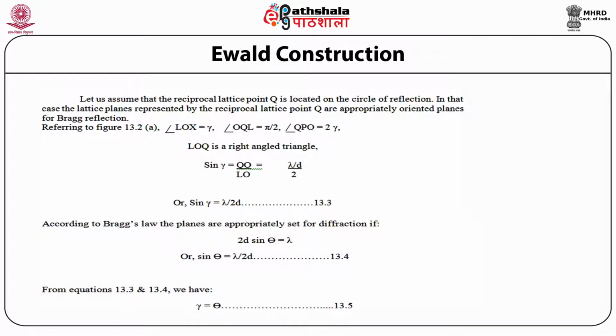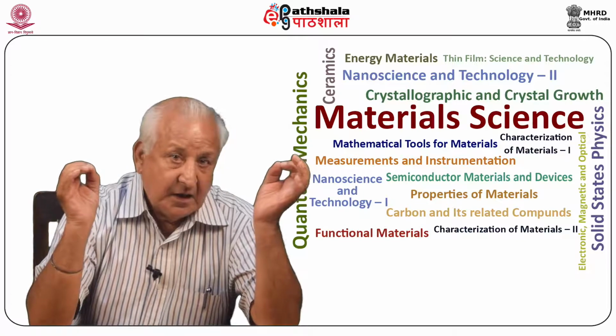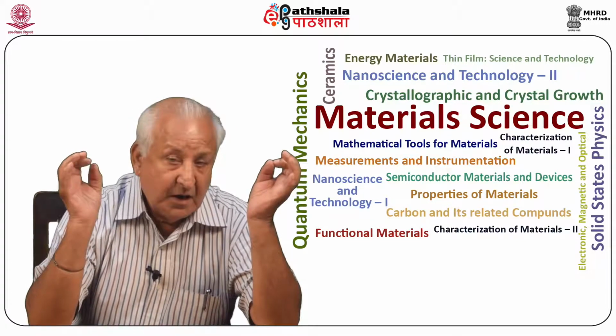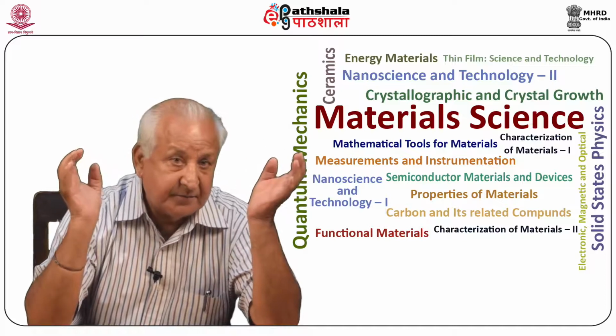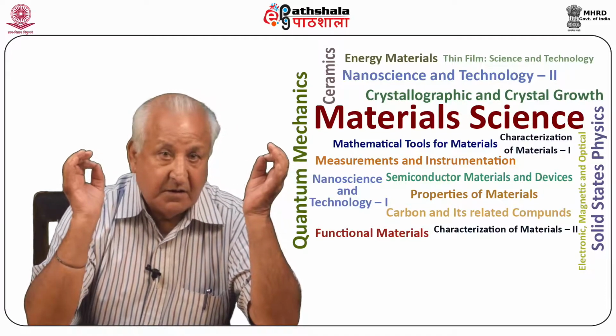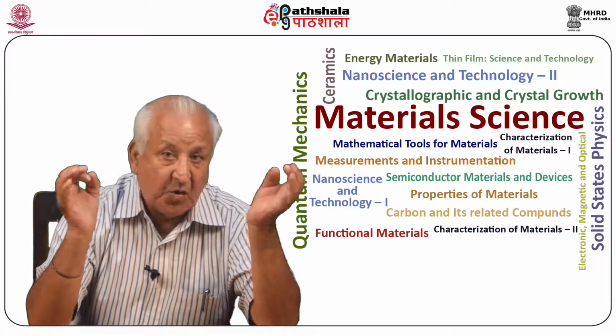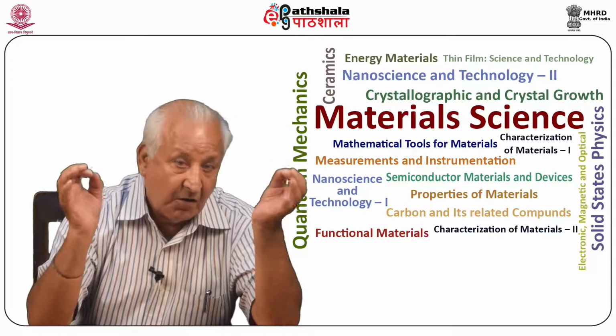According to Bragg's law, the planes are appropriately set for diffraction if 2d sine theta is equal to lambda, or sine theta is equal to lambda by 2d, given as equation 13.4. From equations 13.3 and 13.4, we find gamma equal to theta, which is given as equation 13.5. It suggests that the set of planes which are parallel to XX prime and identified by the reciprocal lattice point Q satisfy Bragg's law.